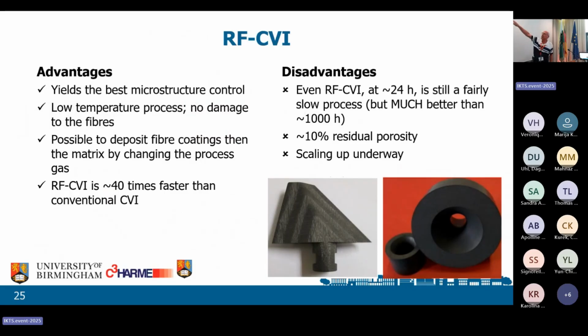So we get the best microstructure, low temperature process, no damage to the fibers, possible to deposit coatings by simply having gas A first and then gas B, up to 40 times faster. Even 24 hours, it's still a slow process. We mustn't get carried away. It's still a slow process, 10% residual porosity. Scaling up is still underway. But we've been making 2 shapes. This one, which is our demonstrator, and we've also been making rocket nozzles. Now that's for a commercial company, a civilian company in Europe.